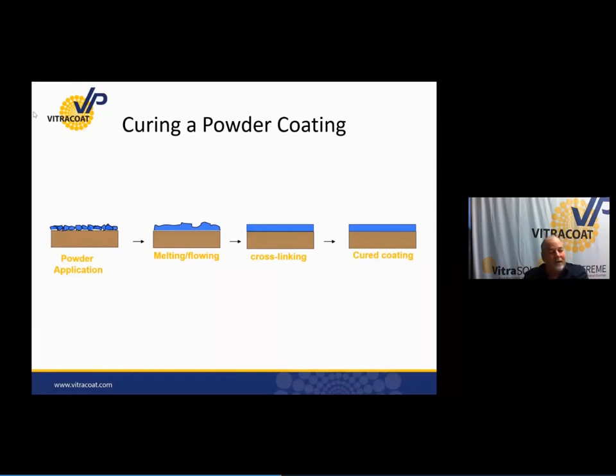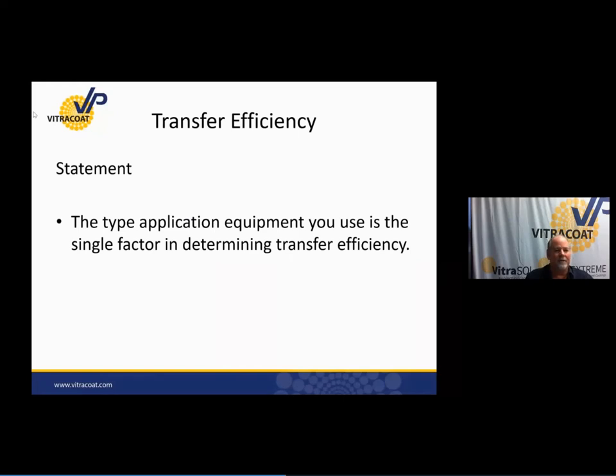I haven't cross-linked yet, but I've started to melt it so that my top coat or my 3rd layer will come on and even adhere to that primer layer, and then I can mono bake those together. So I want to take my primer to the melting and gel stage, and then when I put the top coat on, I want to take it fully cross-linked through all of the cross-linking stage. So that's what gel means as I talk through that process.